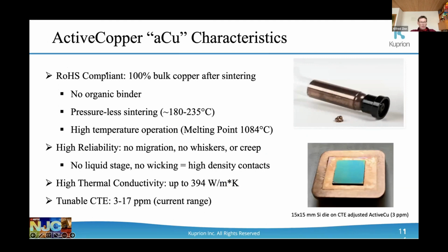So here, the material is RoHS compliant. There's a little further summary. After fusion, it's pure copper, unless there are some CTE adjusters, but there are no organic binders, which you see a lot with silver and other materials that much reduce its performance and its properties. So we purposefully chose not to do that, which is a bit of a challenge, but we were able to work that out. Sintering, it's pressureless sintering in the 180 to 235 range. Typically, we're doing 220 to 230. Depends on the specifics, and it's only a few minutes. It's like more or less a standard solder reflow profile.